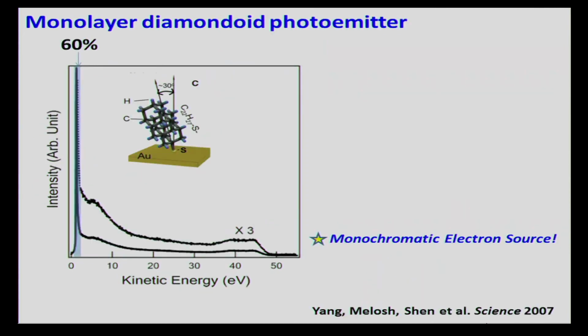So this is what we do. We take, again, a diamondoid, in this case a tetramantane, a 4-caged diamondoid. We modify it with a sulfur atom on the end such that it can be bound to a gold surface. It forms a self-assembled monolayer, that is a monolayer of this diamondoid species standing up on a gold surface. And we shine light on it, and what we care about is how the electron number depends on the kinetic energy.